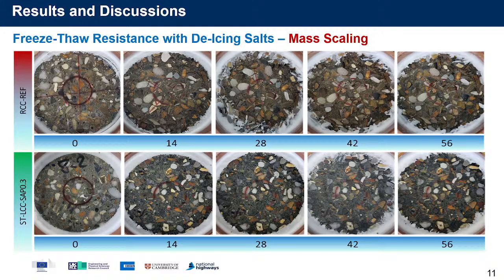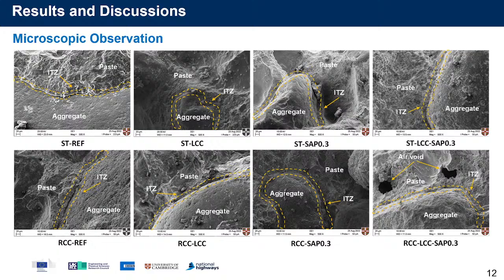And this slide visualizes the surface deteriorations in two groups of mixes, including roller compacted reference concrete mixes and standard lower carbon concrete self-filling mixes. As you can see, in roller compacted concrete the deterioration has moved from the cement paste to detachment of the aggregate, while in the standard concrete mixes it has been mainly limited to cement paste deteriorations.